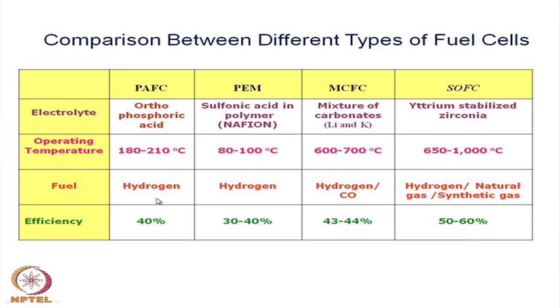Fuel, what is the kind of fuel? In all these, particularly these two, phosphoric acid fuel cell and PEM fuel cell, the polymer electrolyte fuel cell, one needs very pure hydrogen, not contaminated with certain species like carbon monoxide and so on. So, this is one of the limitations, one can say, that you need very pure hydrogen to operate, because there are some catalysts and those catalysts are getting poisoned by the presence of carbon monoxide. Whereas, in the high temperature MCFC, molten carbonate fuel cell, it can operate both with hydrogen and carbon monoxide. So, there is no problem.